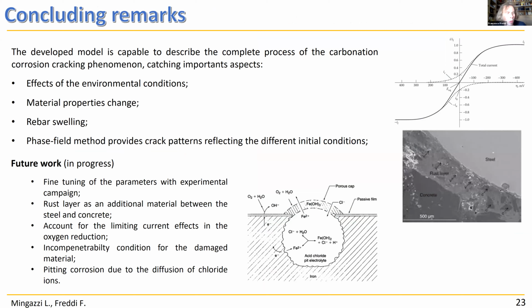So I'm going to conclude. The model that we developed obviously takes into account several things, especially the environmental conditions, the changes of the material properties, the rebar swelling, and the carbonation. The phase field approach permits to determine a crack pattern that in some sense is reasonably in accordance with experimental results. But I think that this is only the first step of a very, very complex problem.